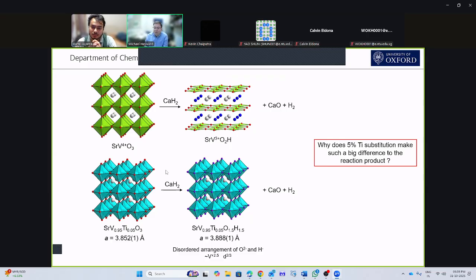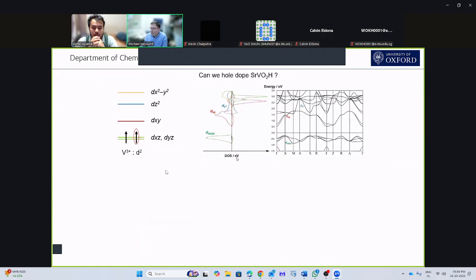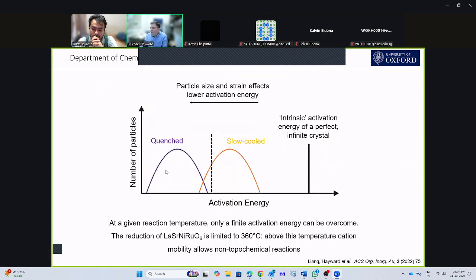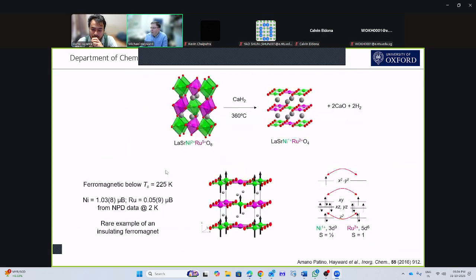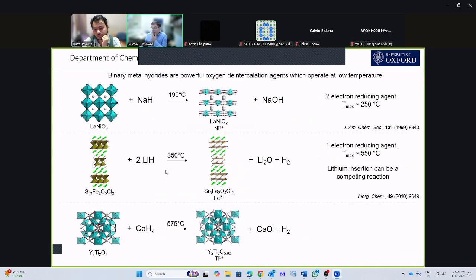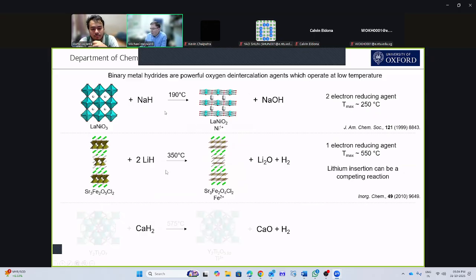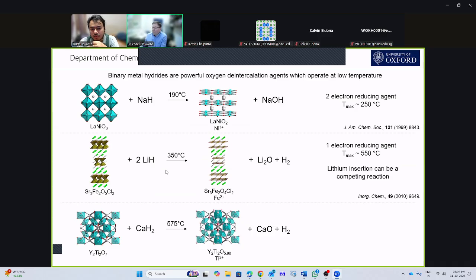And then thinking about the different reagents, well, what we find actually, if I can go all the way back to the beginning, and I've got the list, is that the different reagents behave in slightly different ways because, again, we need to think about the reaction that's happening on the side. So if we think about the sodium hydride case, the reaction from sodium hydride to sodium hydroxide is actually topochemical itself. The structure of NaH and the structure of NaOH are very strongly related. So actually the barrier for the structural conversion from sodium hydride to sodium hydroxide is low. And so that's going to be reactive at low temperature.